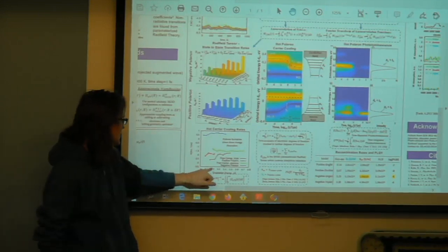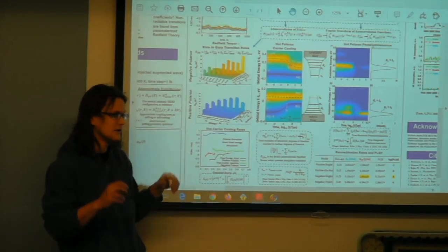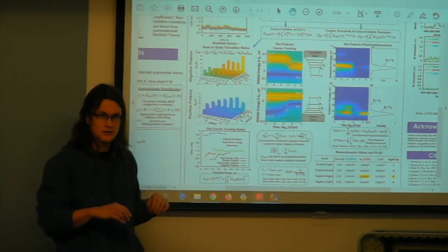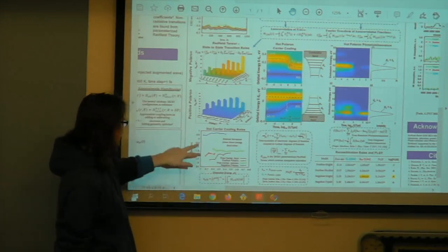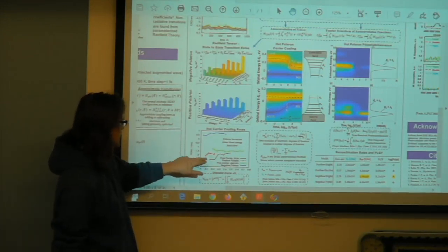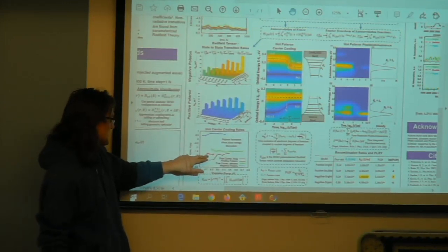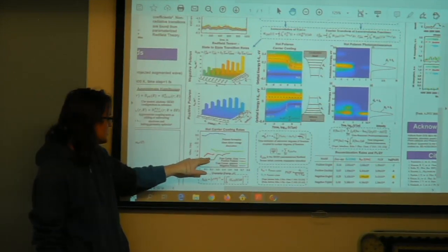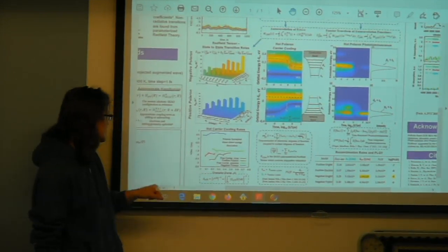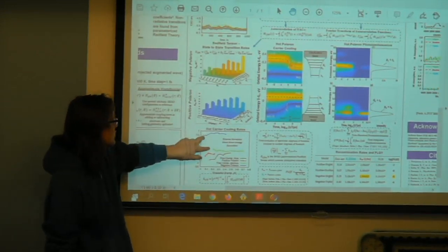And so we plot these for the two cases. When it's a free carrier, not including polaronic effects in the geometry, and then with polarons. The thing to notice here is the red and black compare the positive polaron and then just a hole without polaron formation. We can see that the cooling is slower in this case, and the same trend is shown with the negative polaron.